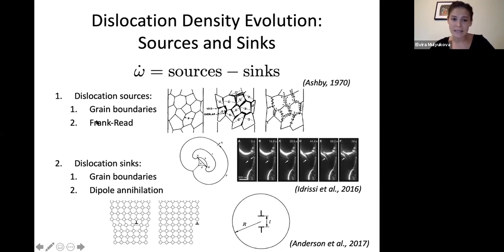Another important source is what's called the Frank-Read sources. This is shown schematically here, and I'll just explain this quickly. What this requires is two pinning points that pin a dislocation at two different ends. Then, due to the applied differential stress, the dislocation pinned at its ends tries to bow out. So A and B here are the pinning points. The applied stress causes the dislocation to bow out, wrap on itself, and form a larger dislocation loop that then continues to emanate outward, while where the pinning points were, the process restarts again. So you have dislocation loops radiating away and increasing your dislocation density.